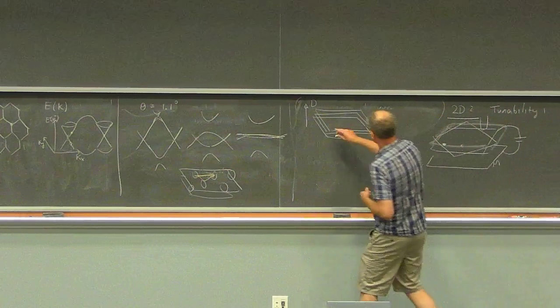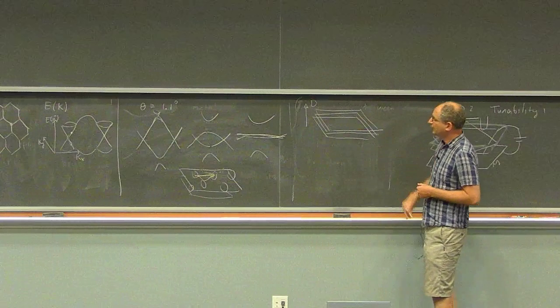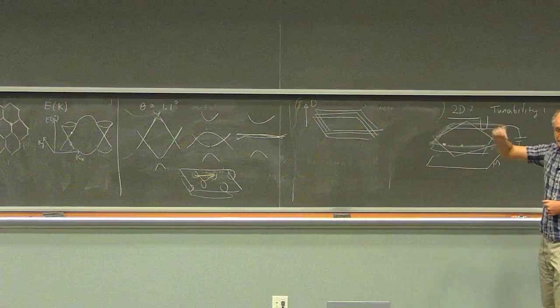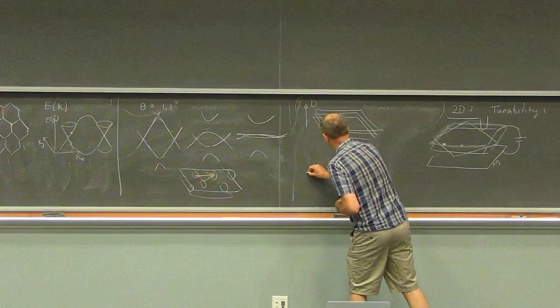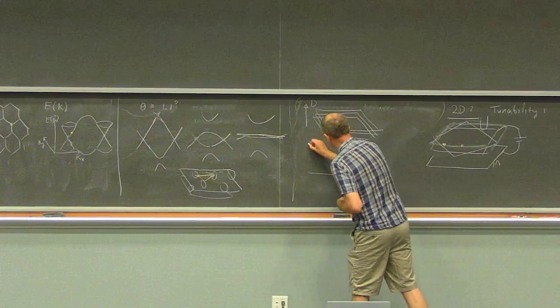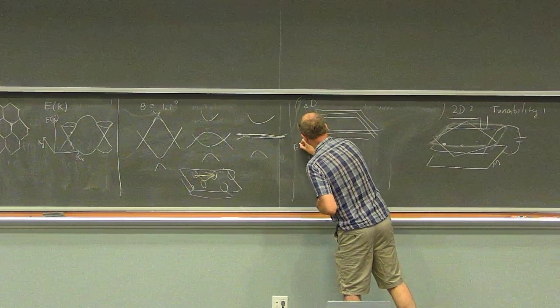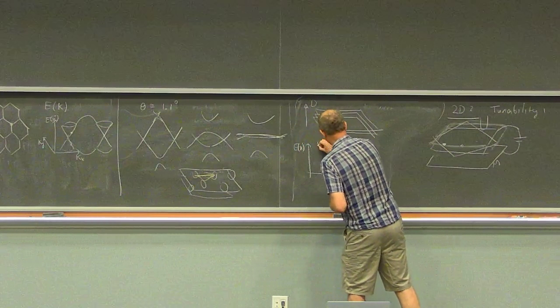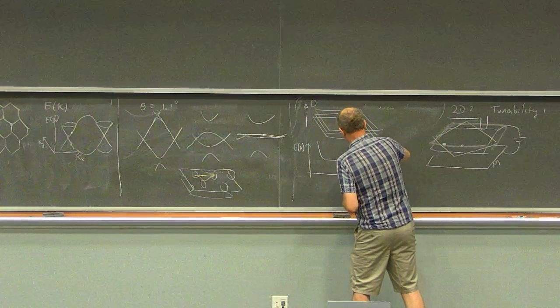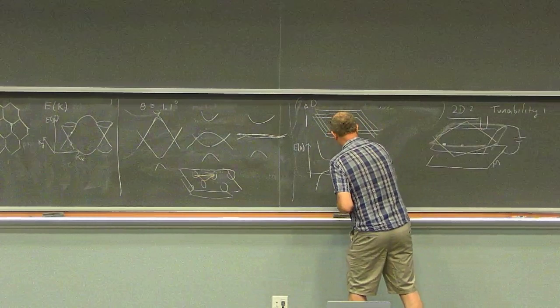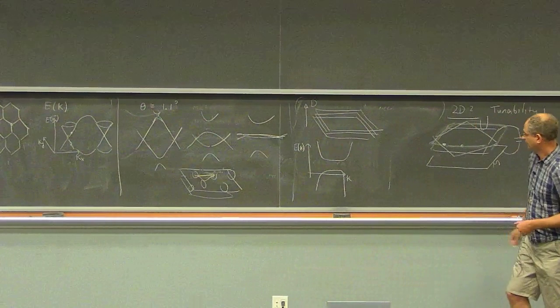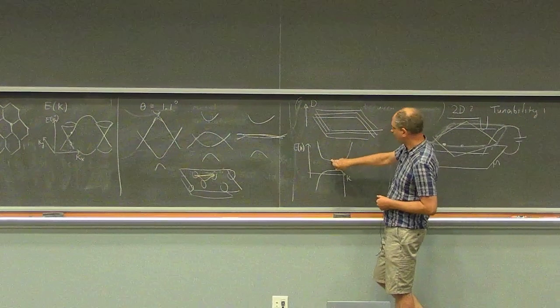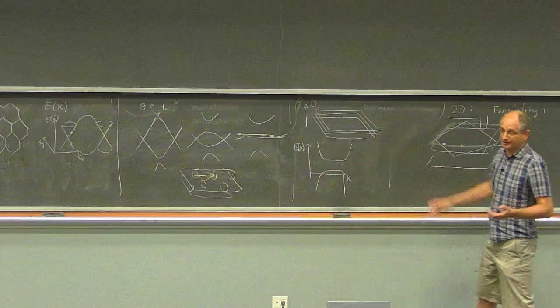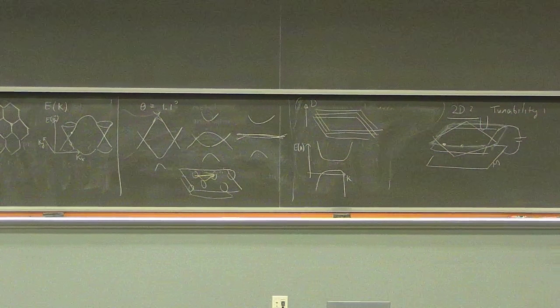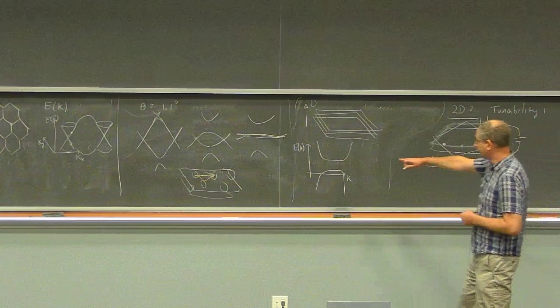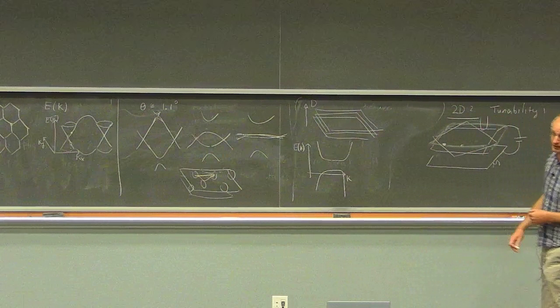But nevertheless, if you look at the dispersion, due to interference effects between the different layers, you can get an energy momentum relation which is again very flat over some range of momenta. So if you create a wave packet somewhere here, it would stay there. It would disperse, but it won't propagate. And again, interaction effects are expected to be very, very strong.